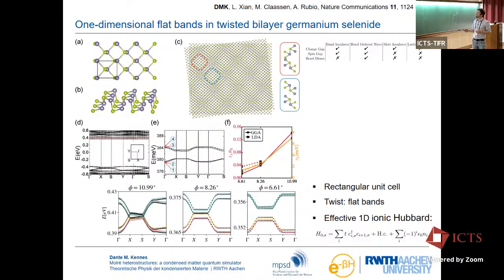Then if you go into this one-dimensional system and you dope somewhere and add a bit of interactions, then you will actually stabilize a Luttinger liquid regime because it's a one-dimensional system. The Fermi liquid paradigm is unstable. As soon as you add interactions, it will actually be replaced by a Luttinger liquid.